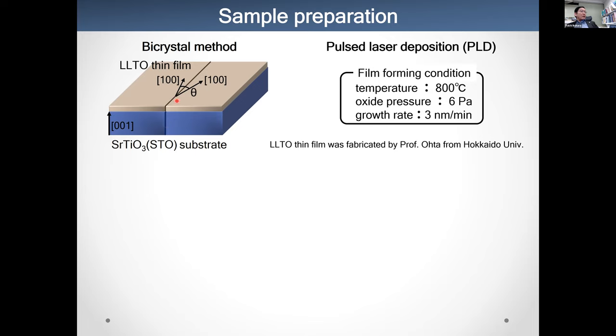For structural characterization, we just polish it from the bottom to the surface, and the ion thinning is conducted from the bottom. Then we can characterize the atomic structures. So we don't need to remove all of the substrate, just to the surface. The ESM method is also fine even when STO is attached; there's no effect. Okay, so it's just classical polishing and ion milling. That's right, that's classical. Okay, thank you.